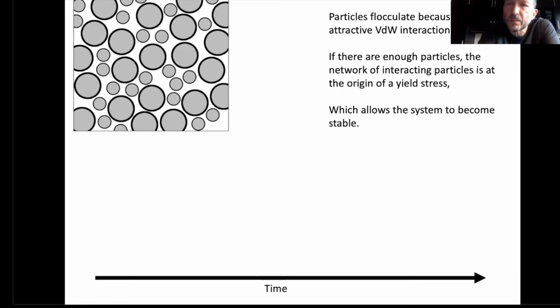So all in all, cement pastes are unstable by nature because cement grains are either too heavy or too coarse to be suspended in water. But particles do flocculate because of some attractive van der Waals interaction at the level of the cement grains' surface defects or surface asperities. If there are enough particles in the system, so a water to cement mass ratio that is low enough, the network of interacting particles is at the origin of a yield stress. And this network is so strong that it is able to keep the particles captured, preventing them from moving, which allows the system to become stable and provides a cement-based material that can be used by industry because it is stable.